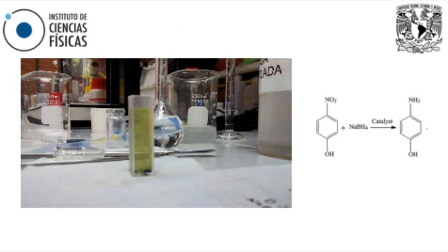So actually we did the video proof. This is the nitrophenol with the catalyst, and it is not plenty, it is 0.5 milligrams, very little. And we just added sodium borohydride. The time lapse of this video is 120 seconds, keep that in mind. You can see the transformation of the nitrophenol, which is yellow in color. Within 120 seconds, the yellow color disappears and you get a pure white, colorless solution.